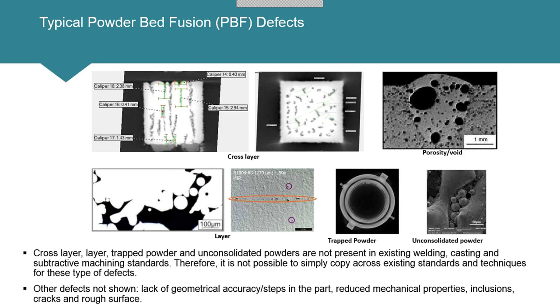A couple of slides on the types of defects, which we have firstly generated mainly from research projects at the MTC, and most of them also from AMAZE basically. So these are some of the defects that we find only in additive manufacturing. These are typical powder bed fusion defects. Some of them are electron beam melting, and some of them are laser powder bed fusion. But mainly, this is to highlight those types of defects, for instance, cross-layer defects. Those images you see there are slides of the X-ray CT. It's a vertical cut on the left, and the top of the build layer slice, just to show the morphology of the defects, which typically don't occur in the other methods, basically.